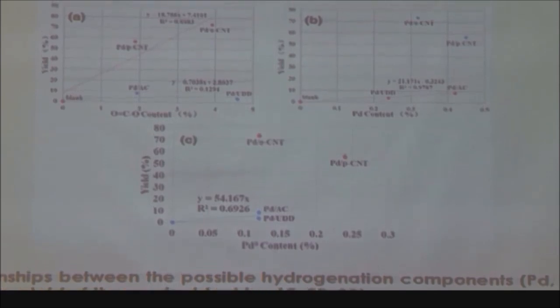Again, we have three materials: nanodiamond, carbon nanotube, and activated carbon. We were not sure whether the support was playing some role in this work. We just found a correlation that whenever the palladium content increased, the HDO capacity, the hydrodeoxygenation capacity, also increased. But no such correlation was observed for any of the functional groups or the surface. For example, what nanodiamond is doing or what the activated carbon is doing, we were unable to get any information from this work. Even though we were able to publish it in the Journal of Energy Chemistry with impact factor 10, this was still a limitation in our work and we were unable to explain it.